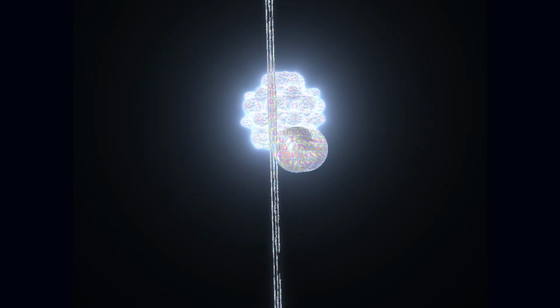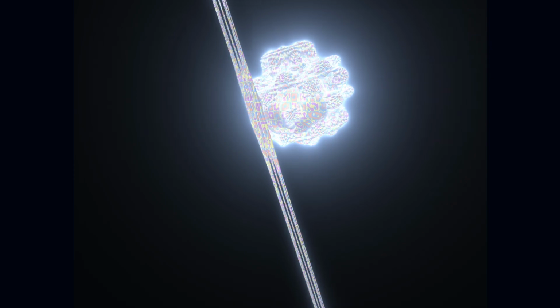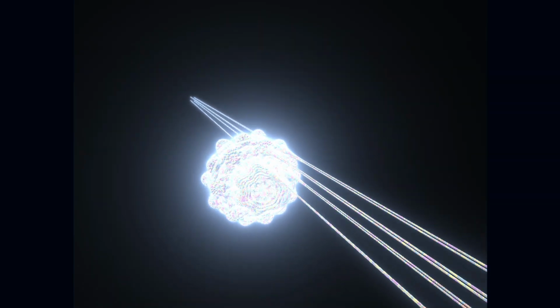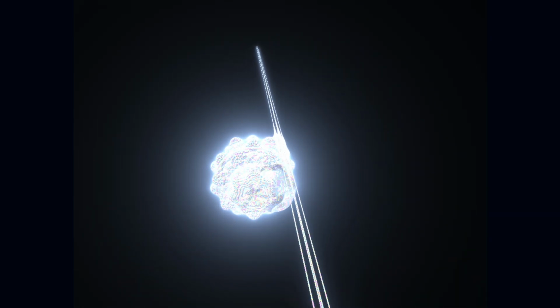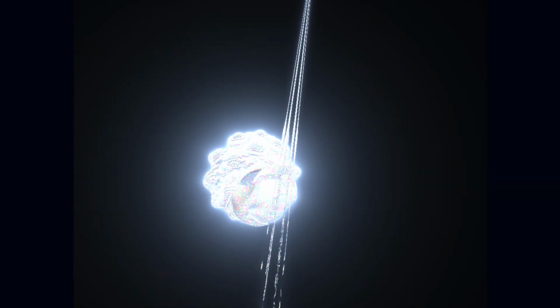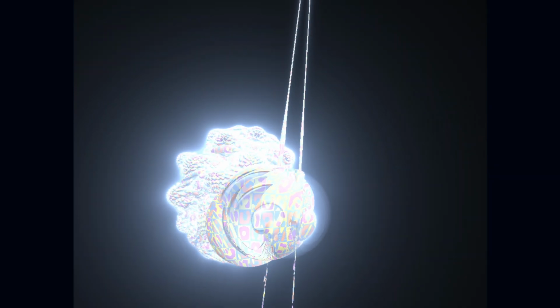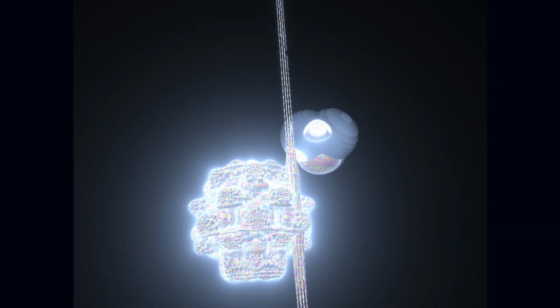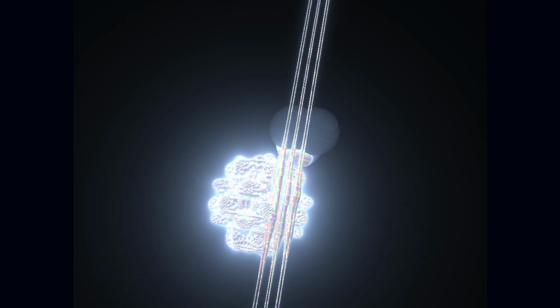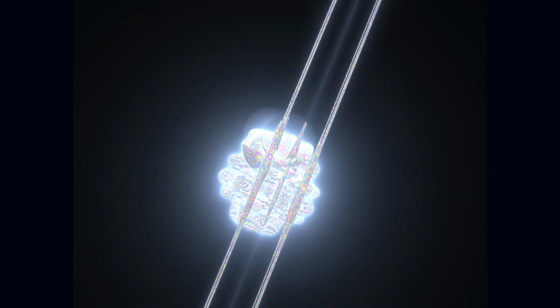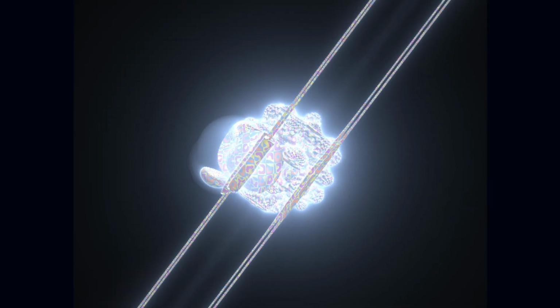However, you hinted that polaron formation isn't always a bad thing. There was this polaronic protection. Yes. It's quite intriguing. In certain soft, ionically bonded systems, like those halide perovskites we mentioned. The solar cell materials. Exactly. The phonon cloud that forms the polaron can effectively shield the charge carrier from scattering off other things, like charged defects or even other carriers. So the baggage protects it. In a way, yes. This polaronic protection can lead to surprisingly long charge carrier lifetimes and diffusion lengths, even in materials that aren't perfectly ordered. And those long lifetimes are highly desirable for applications like solar cells and LEDs. So sometimes a little extra baggage is actually a good thing. I love that idea of polaronic protection.